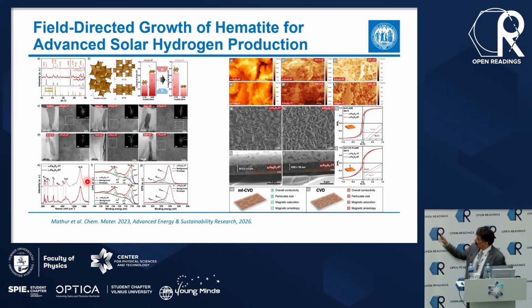What it shows is that if you grow a catalyst in a magnetic field, it is not degrading, whereas the one which is not deposited in the field, same material, degrades, because now you can control the grain boundary. You already make the catalyst in a preferred, more stable state. And this is what we have looked into in detail. What is happening when you are applying a magnetic field? One thing is that you promote the diffusion of ions. Field is promoting, so you have larger domains.